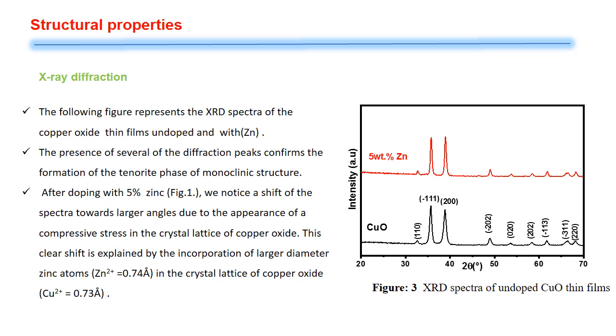The following figure presents the XRD spectra of copper oxide, undoped and doped with zinc. All films show the formation of the tenorite phase of monoclinic structure with space group C2/c. After doping with zinc, there is a displacement of the peaks, which represents the occupation of the copper ion sites by zinc ions.